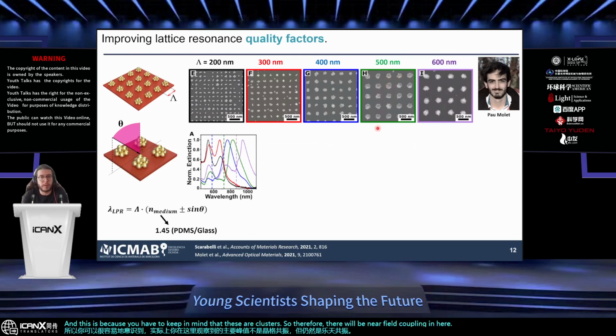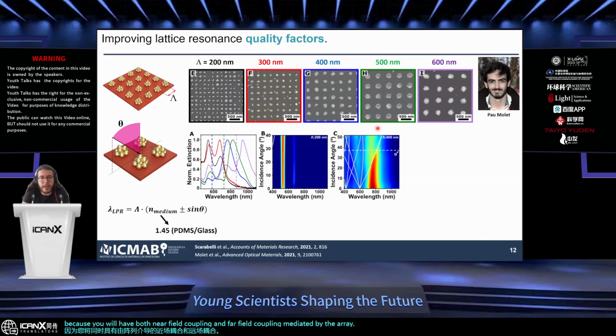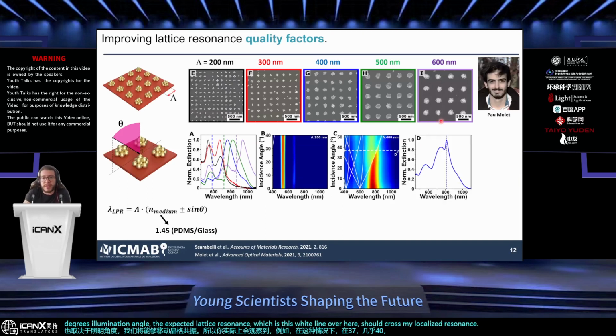Basically, this system is much more complicated because you will have both near field coupling and far field coupling mediated by the array. This is just to explain the importance of doing a complete characterization where we also change the illumination angle. Since the lattice resonance depends on the illumination angle, we will be able to move the lattice resonance. So you will actually observe that, for example, in this case, at almost 40 degrees illumination angle, the expected lattice resonance, which is this white line over here, should cross my localized resonance and appear over here. And that's exactly what we see.